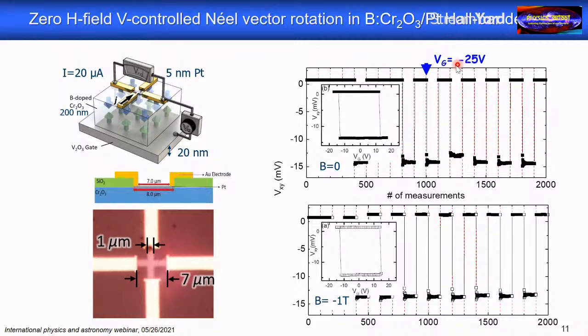So we apply minus 25 volts, and then we switch from the zero state into a state with a sizable transverse voltage. And if we take a couple of measurements, nothing changes. But if we apply the positive voltage again, then we switch back. And we can do that over and over again in a non-volatile, reliable way. Now, if we apply a magnetic field, and that's an important insight as well, nothing changes. So that means this entire switching effect, as we see it here, has nothing to do with the fact that a magnetic field is present.